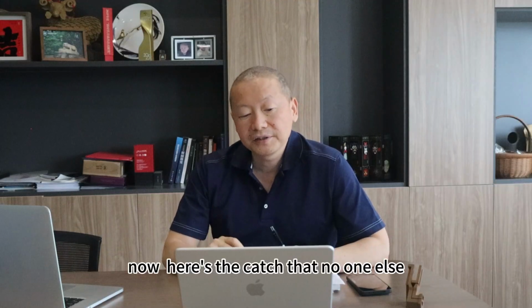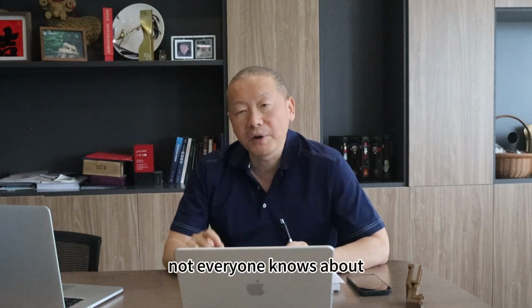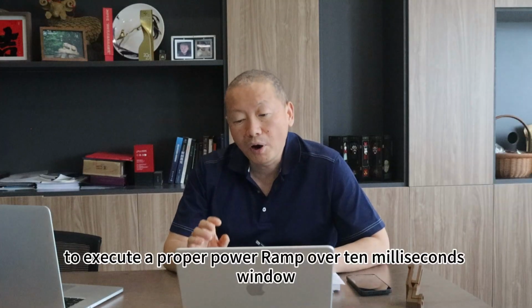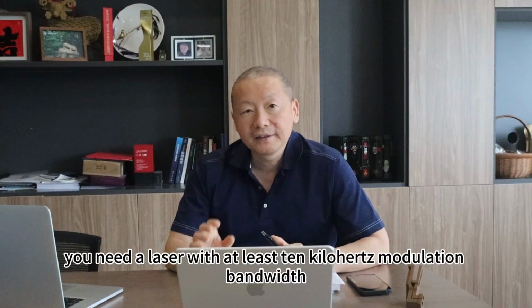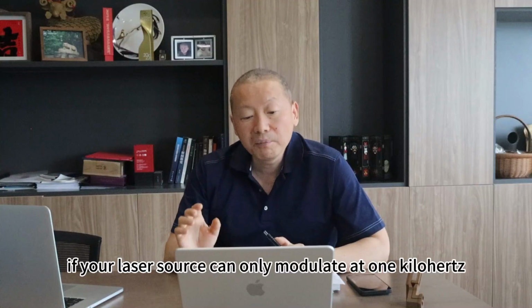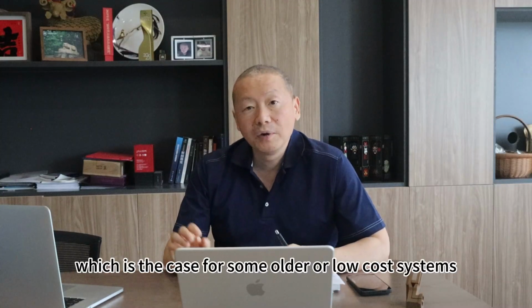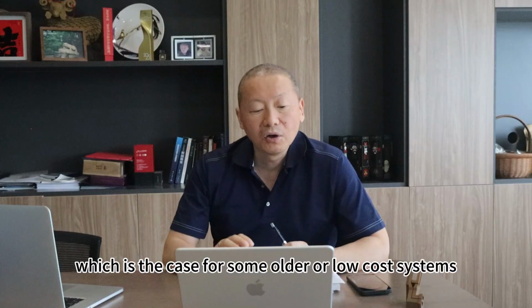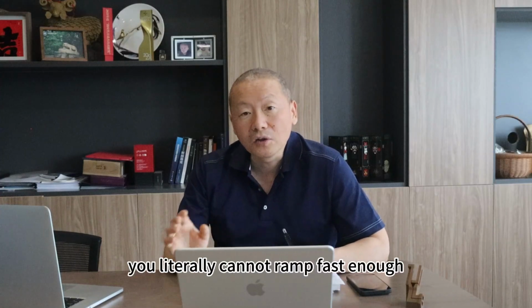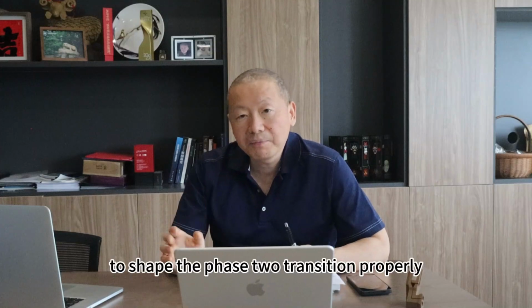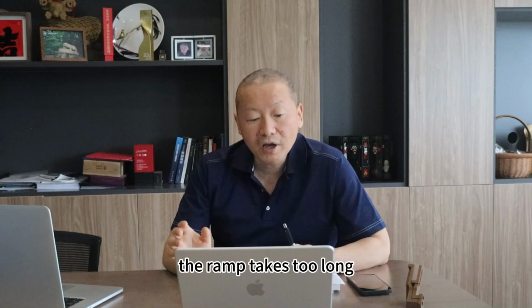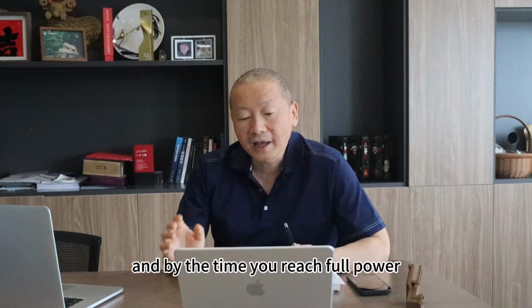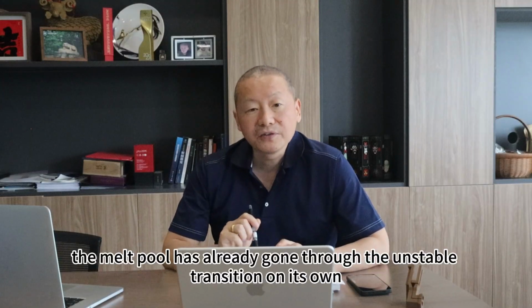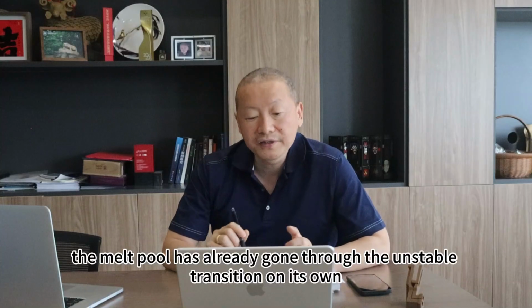Now, here is the catch that not everyone knows about. To execute a proper power ramp over a 10 millisecond window, you need a laser with at least 10 kilohertz modulation bandwidth. If your laser source can only modulate at, say, 1 kilohertz, which is the case for some older or low-cost systems, you literally cannot ramp fast enough to shape the phase 2 transition properly. The ramp takes too long, and by the time you reach full power, the melt pool has already gone through the unstable transition on its own.